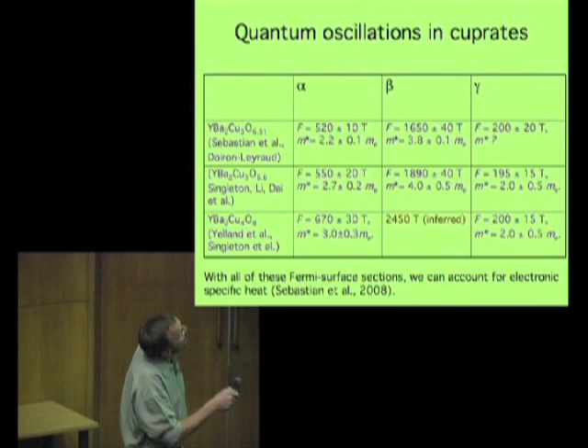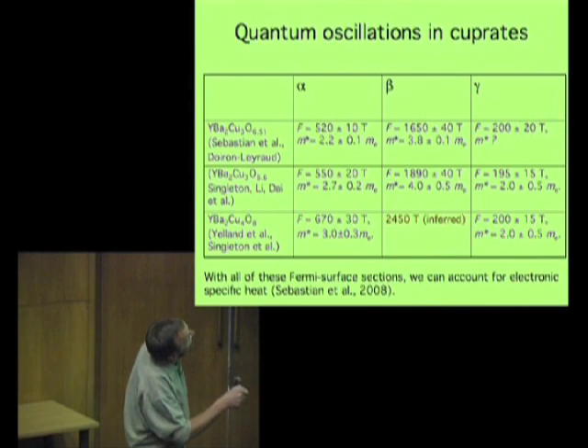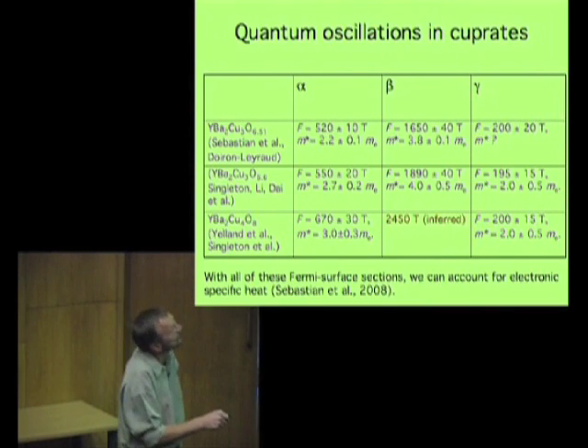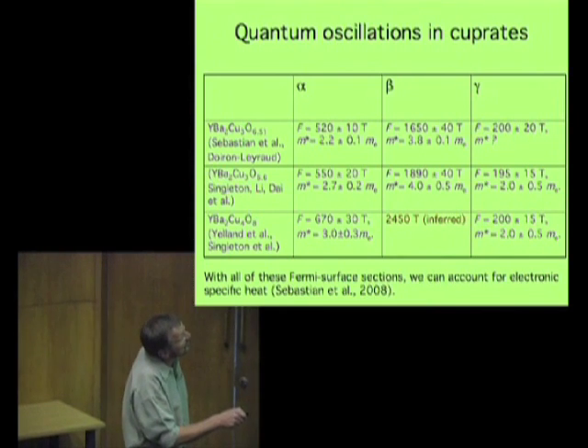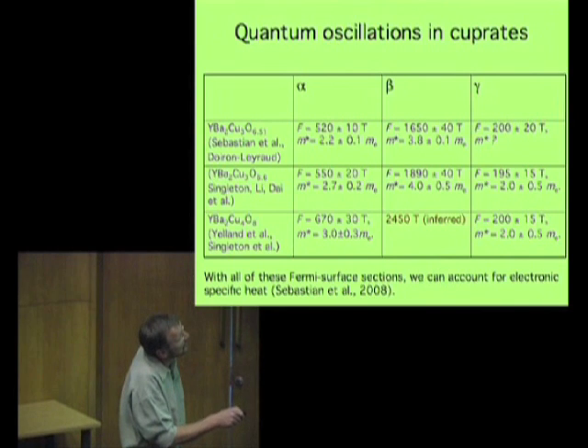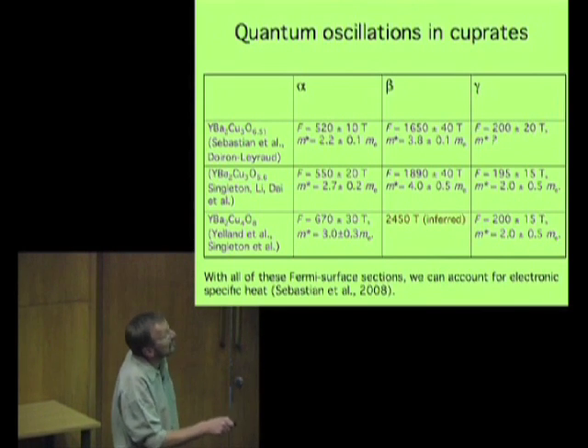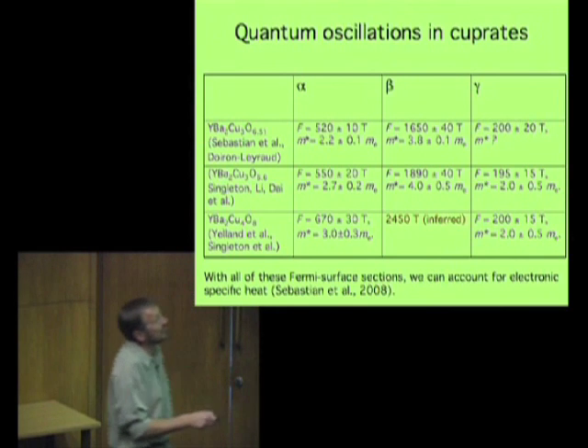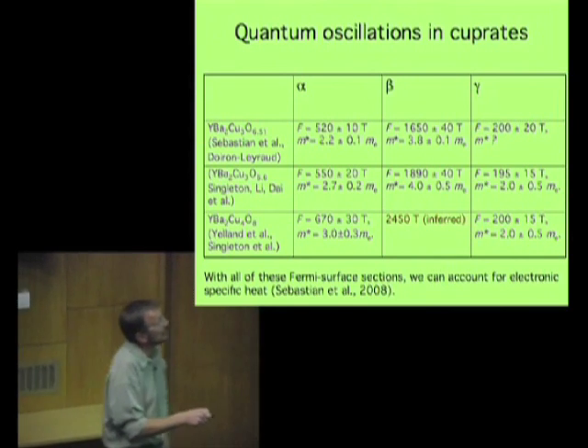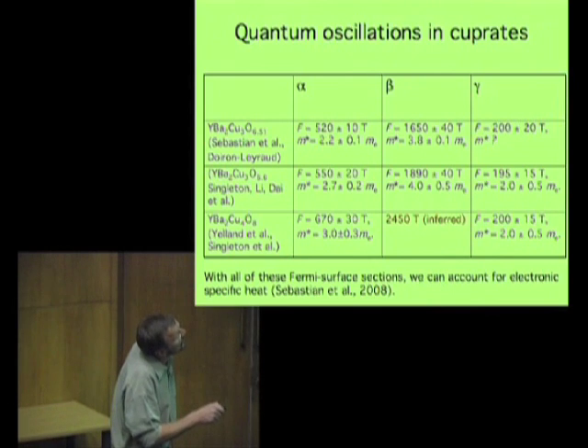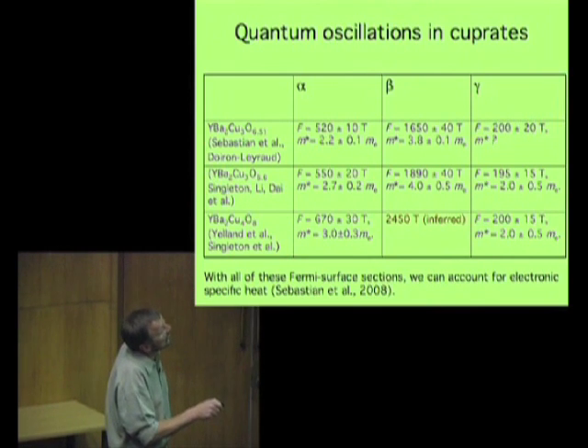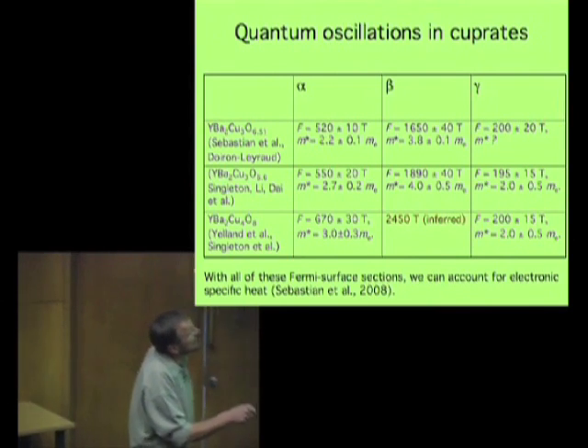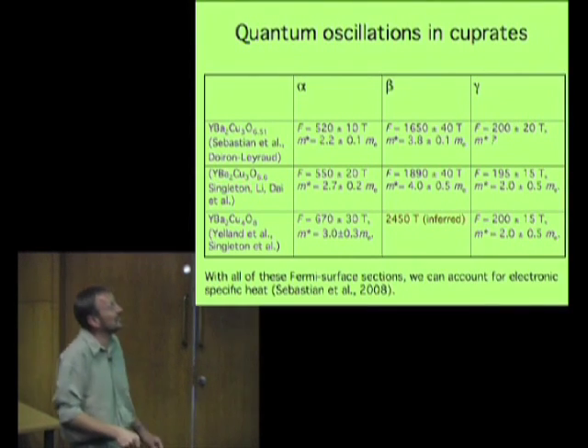So as you can see, there's this 520 Tesla frequency in the low doped one, which grows to 550 Tesla as we crank up the holes a bit, which grows to 670 Tesla as we put more holes in still. There's this low frequency that I pointed out, which was just seen as a kind of background, which seems to stay around 200 Tesla, although it's very difficult to get an accurate frequency in spite of what's quoted in these various preprints and papers. And then there's this high frequency, which is discovered in these top two, which has been inferred from the way in which the other oscillations behave in this third one here. And again, this is increasing as you go up in hole doping.